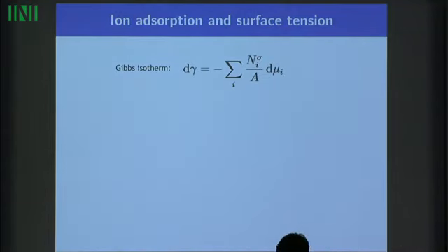So here the idea is that you have ions from the solution adsorbing preferentially on the surface. As soon as you have a difference in affinity of the ions for the surface, you get a charge distribution in the interfacial layer, and as soon as you apply an electric field, you induce a shear there, and that can actually produce a non-zero mobility. Of course, what you need to know is exactly the affinity of the ions for the surface.